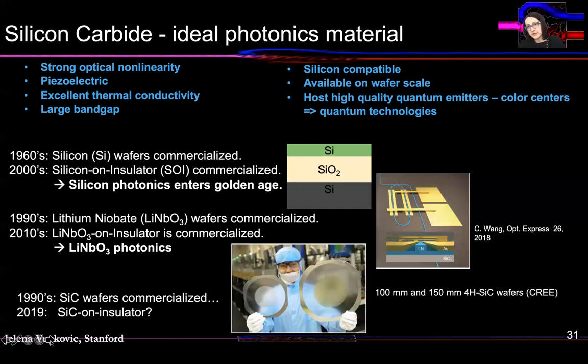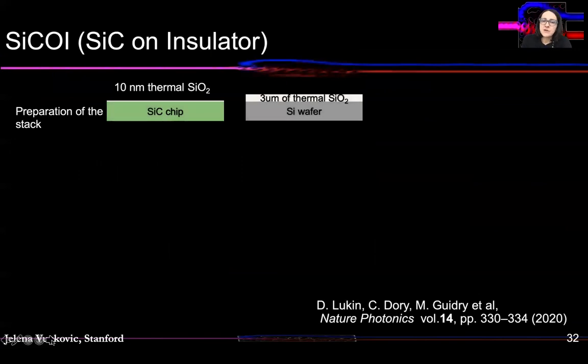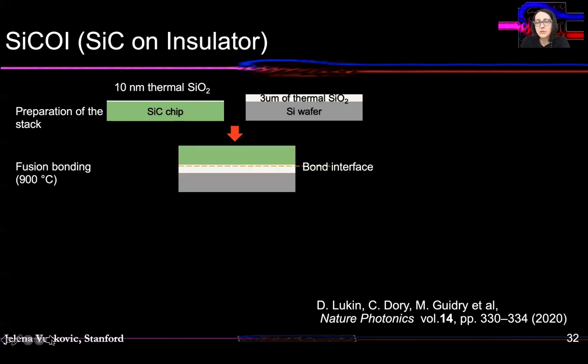And although we believe that silicon carbide is a much better photonics material than both of these two, silicon or lithium niobate, because no other material allows you to do everything that's highlighted on top of this slide, as of now, there is no really commercial high-quality silicon carbide on insulator, although some companies are trying to develop and market it now. But we can actually get very high-quality bulk silicon carbide wafers, even 6-inch wafers from companies like Cree. For that reason, my team developed a process for producing pristine films of silicon carbide on insulator.